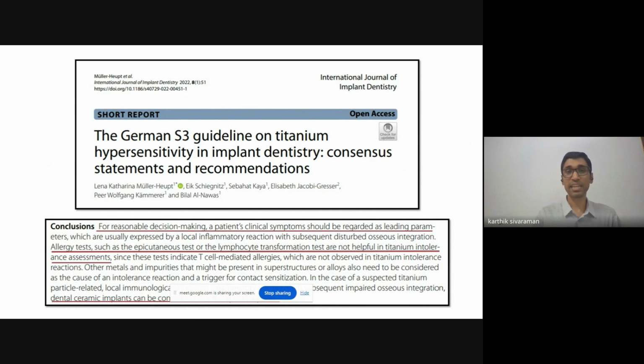Importantly, allergy tests such as the epicutaneous test or the lymphocyte transformation test are not helpful in titanium intolerance assessments. In case there is a localized inflammatory response, the implant has to be removed, and you can consider a dental ceramic implant as a therapeutic alternative. So this is regarding titanium hypersensitivity: an extremely low prevalence, and it's not easy to diagnose in a patient either.